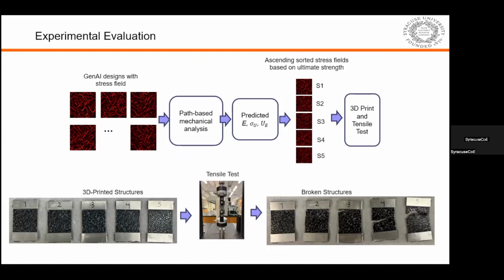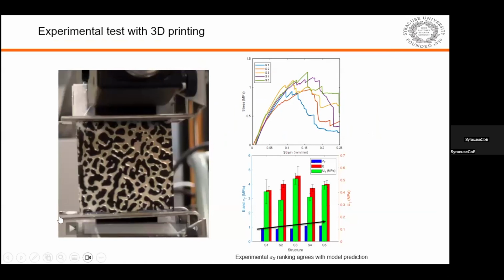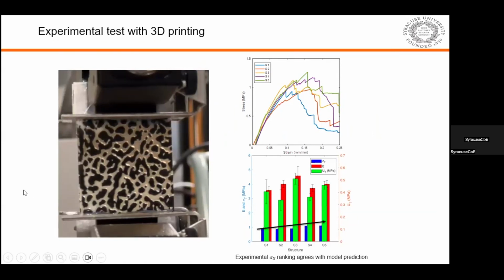And then here's the summary of the workflow. Generative AI generates the design of stress field together with the material distribution. And we use the path-based mechanics analysis to predict Young's modulus, strength and toughness. And then we can sort those conformations by certain order. For example, here we sort it by the ultimate strength. And then we can turn that into 3D printed structures. We use our tensile machine to do the test. These are broken structures. And here's just a movie showing the test process.